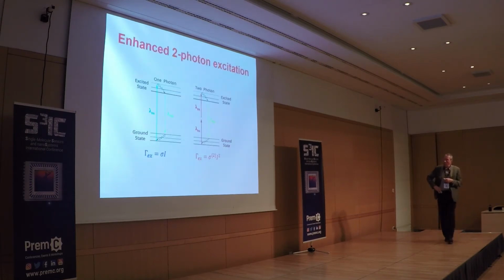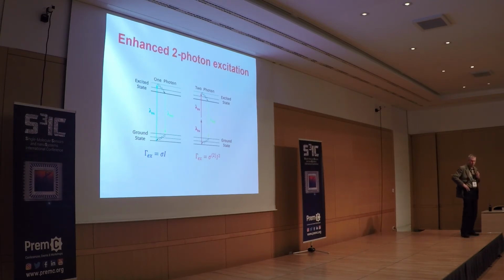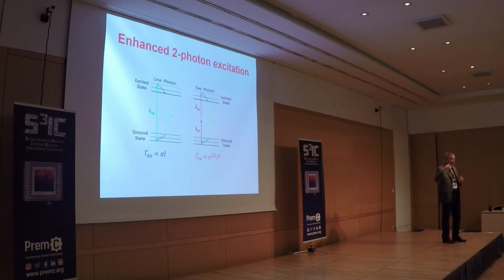All right, so more recently we looked at two-photon excitation. That's another question that we had. Of course, it's a potentially very attractive experiment to do, because you realize, for example, in surface-enhanced Raman scattering, you can enhance Raman scattering because you enhance the field that comes in, and you also enhance the field that comes out. So there is this factor of enhancement which comes twice. You enhance by the field enhancement factor squared because of the incoming field, and you enhance the second time upon emission by the square of it, so it's the enhancement factor to the power 4.